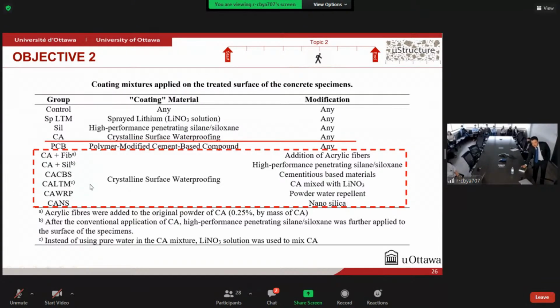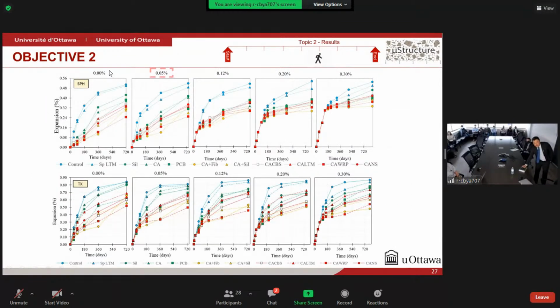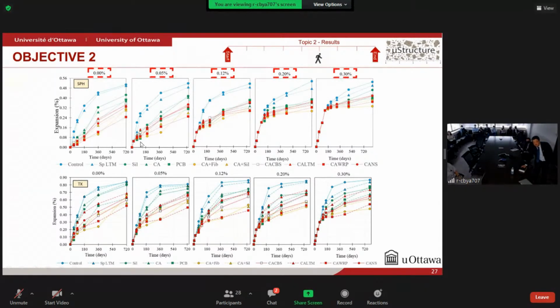and nanosilica. As we can see with the results, no matter the initial expansion development of the concrete before the application of the products, once we treat the surface of the concrete specimens, we have a change and a decrease in the final expansion development of the concrete. The only exception here is the treatment in which we sprayed lithium on the surface of the concrete specimens, that shows similar behavior to the control specimens.